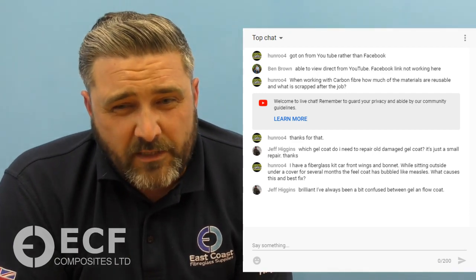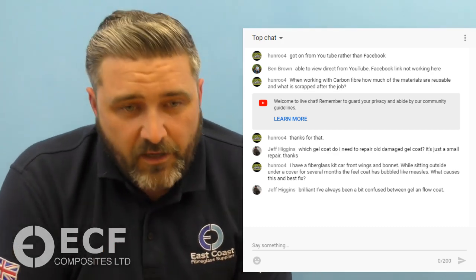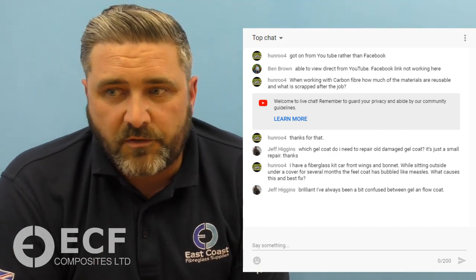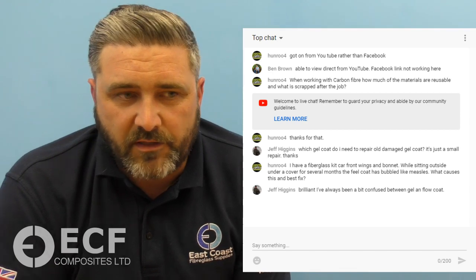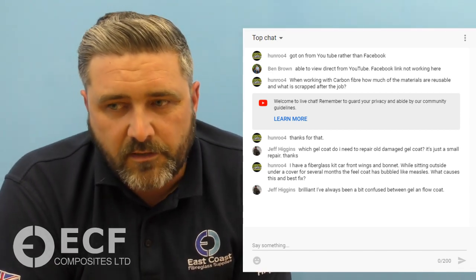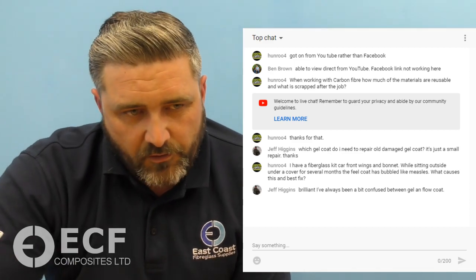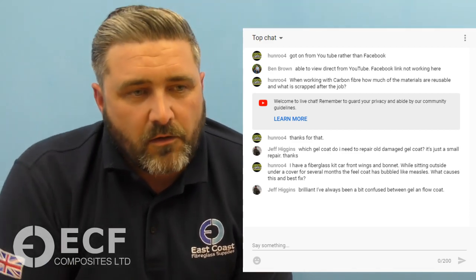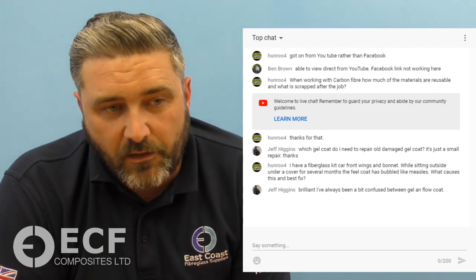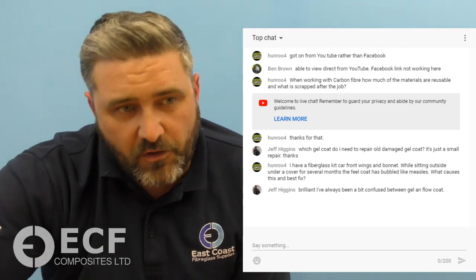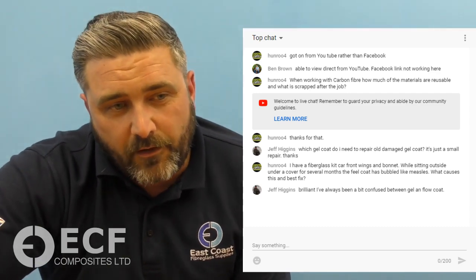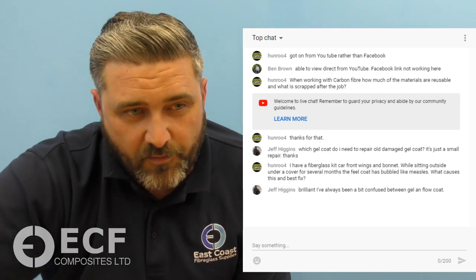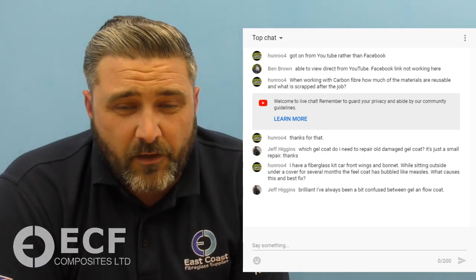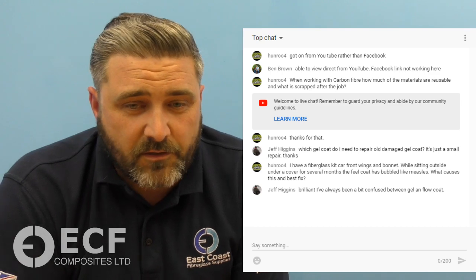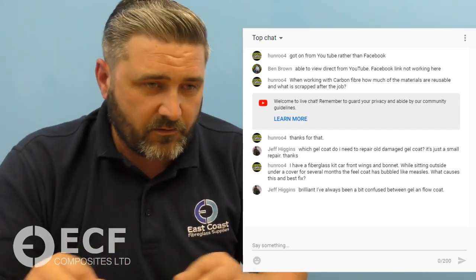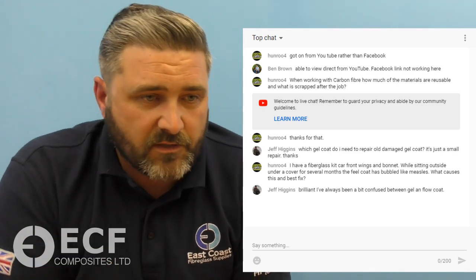If you want to keep it polyester, you can do the same thing, sand it right back. I believe in the automotive industry, when they're repairing these, they usually give it a tissue layer with a polyester resin, just to give it a stronger surface coat, and then they'll go over with a layer of gel coat, and then, as I mentioned earlier, they'll finish it off with a flow coat. But you've got to be confident that that's your last coat and you've got enough thickness there to start rubbing it back. The downside of that process is that some areas might be too thick of gel coat, so if it's a flexible panel, you could end up with little star crazes and cracks and things.